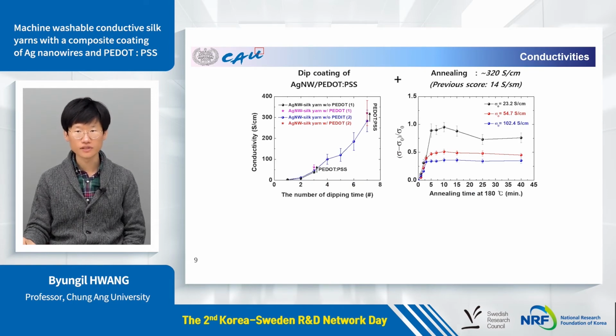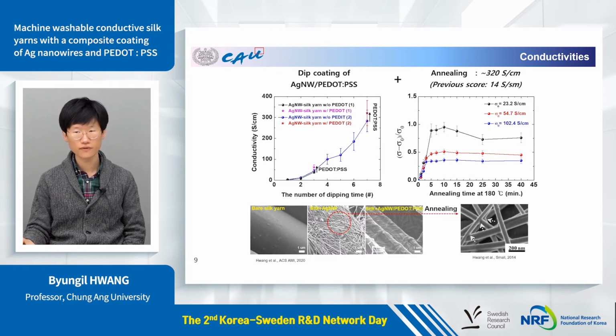The conductivity of the fibers could be controlled by the number of dip coating cycles. As you can see in the top left figure, the conductivity increased as the dip coating number increased. In addition, the conductivity could be further enhanced by the post-annealing process. As the post-annealing time increased, the conductivity also increased. During post-annealing, the silver nanowire networks formed junctions that supported electrical current flow, thereby enhancing the conductivity. With the combination of the dip coating and post-annealing processes, our conductive yarns showed about 320 S per centimeter of conductivity, which was much higher than that of PEDOT:PSS-only fibers, the previously developed ones at Chalmers.